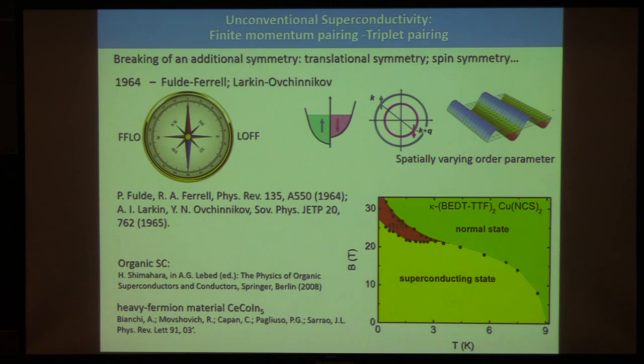So this was a challenge, but what these four gentlemen showed is that there actually is a solution to this, and the system, nonetheless, under certain conditions, will condense. It will choose one particular momentum, Q, in real space, so it will break translation symmetry, and will form an order parameter that is now oscillating in space, and will have these kind of pairs that have now a finite momentum in space. And this state, as I mentioned, is called the FFLO or LOFF state.